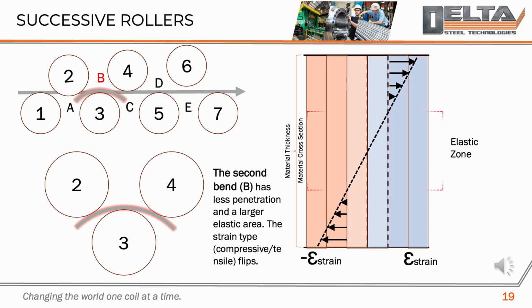Now let's take a look at what happens in the second bend, the letter B in this case. At this point, the material reverses direction, but the bend isn't as deep as the first one, meaning there's less penetration. The top fibers are now being stretched, reaching about 2.5 yield strains, while the bottom fibers are being compressed to 2 yield strains. What's key here is that the elastic zone grows, creating a larger area that hasn't been